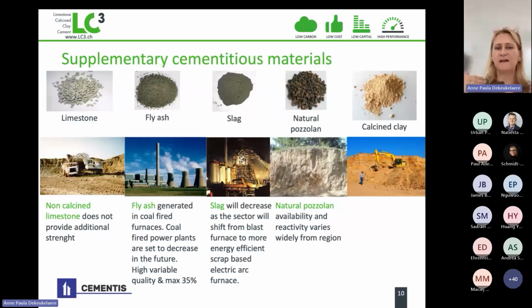So let's go one step back and say, okay, what would be the supplementary cementitious material that could replace clinker? So we have different elements. We have limestone. Limestone is in the recipe of LC3, but limestone alone will not provide additional strength, which means that you may add limestone to your recipe of cement, but only to a certain percentage. Over that, your strength will decrease. Second option would be the fly ash. Fly ash is generated from coal-fired furnaces. And we know that coal-fired power plants are set to decrease in the future. So the availability and the quantity of this waste will decrease and will disappear one day.